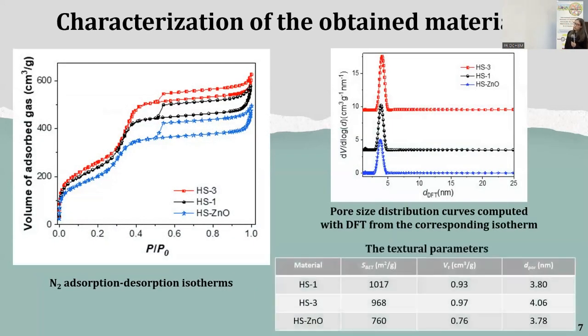The nitrogen adsorption desorption isotherms are characteristic for mesoporous compounds. The textural parameters are determined from the corresponding isotherms, such as specific surface area and total pore volume. They have high values, which means a high porosity, and hence the possibility to accommodate a high amount of organic molecules. The pore size distribution curves were determined from the corresponding isotherms by density functional theory.